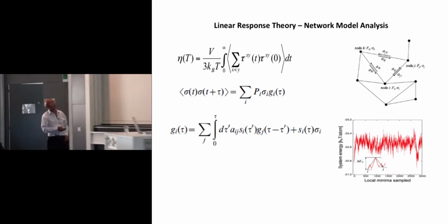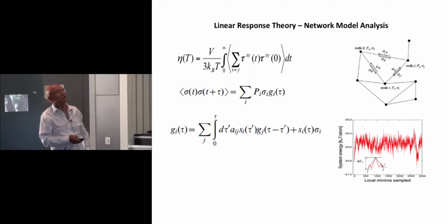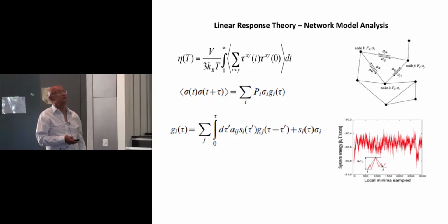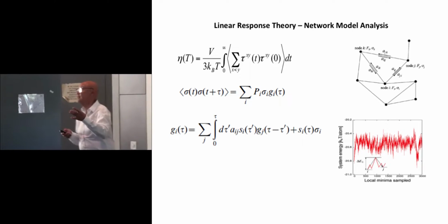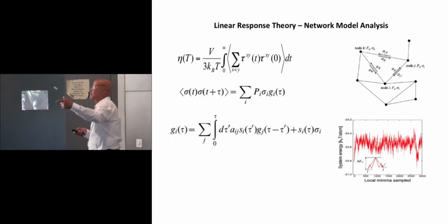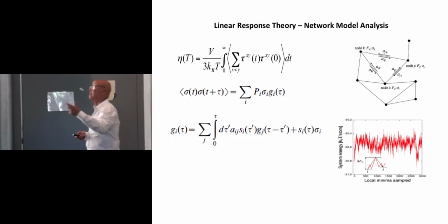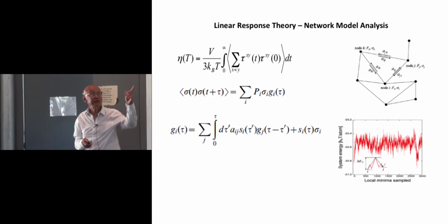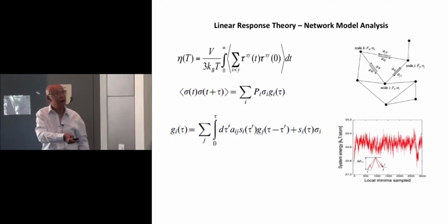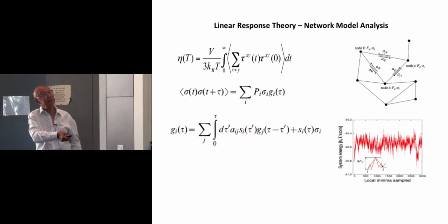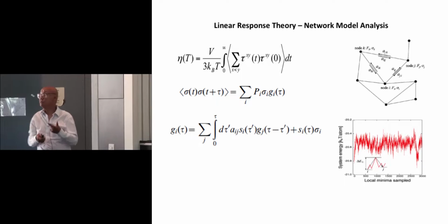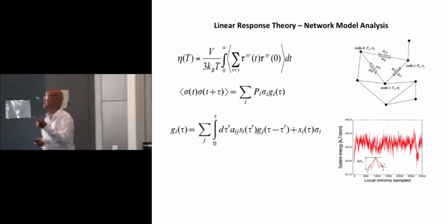So this is the Green-Kubo network calculation. Basically, by network, we simply mean you can imagine there's a network of nodes, various sites, and the sites go from one site to another site through some kind of activation. So if I have activation energy from the lower part, I can map this information onto a matrix whose elements are the activation probabilities.